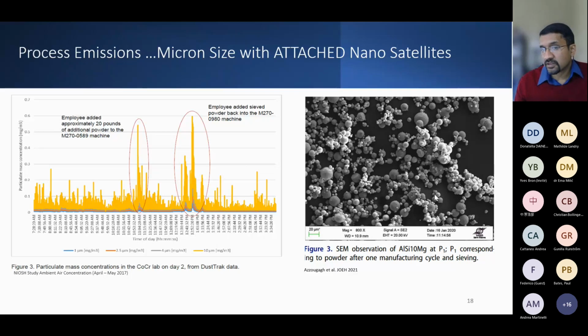They're adhered to the surface because for any nano material, if you work with it, it takes quite a bit of processing to make sure they are dispersed fully. So in this case, we knew our fumes side was the reactive, which was getting collected on filters, but it's addition of materials which are effectively of the same alloy composition that adhere to it and create these satellites. That was one piece that helped me think through why that increase in reactivity happens as you collect these fumes. But they don't necessarily transform or tend to be in the nano regime. They are actually agglomerated onto the primary particle and then end up creating these particle sizes.